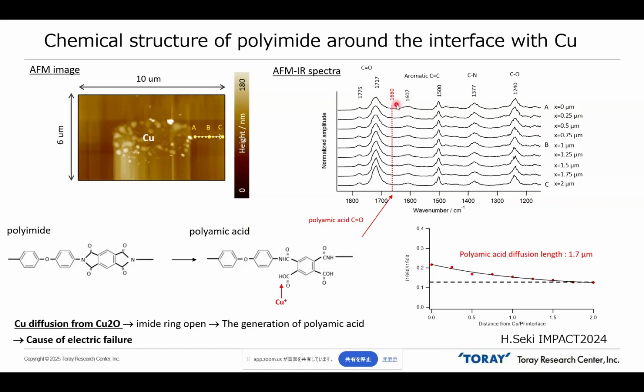But if we plot the intensity of this wave number, the intensity is high around the interface with copper. Then this intensity is decreasing with the distance from the interface. Then this wave number means this kind of chemical structure. So in this experimental result, we can also say that the polyimide structure is decomposed, destroyed.